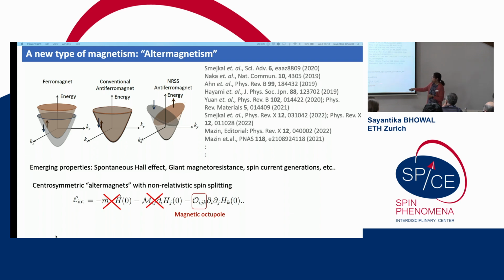Now, if we look at this magnetic multipole expansion, then we can, of course, ignore this net dipolar term because it doesn't have any net magnetization. It is also inversion symmetric, so this kills the second order term, that is the magnetoelectric multipole term, and hence the magnetic octupolar term is the lowest order symmetry allowed magnetic multipole which can have ferroic ordering.